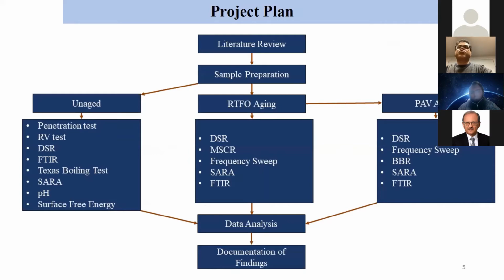Here is a snapshot of our project plan. In short, we did the literature review. Then after sample preparation, we tested asphalt binder unaged, RTFO aged, and after PAV aging. And then we did Superpave tests as well as selected chemical tests. We also did a very limited, I would not call it mixture, but a loose mix test. We did the Texas boiling test to see what kind of binder retention there would be with different aggregates. Then we came up with concluding statements based on, again, a limited study. Next.